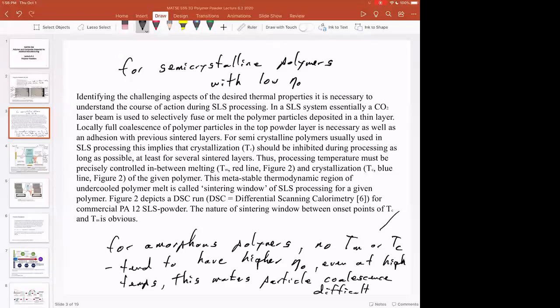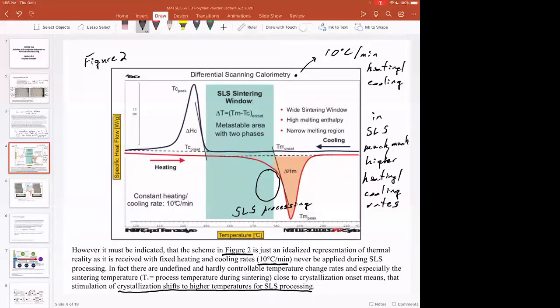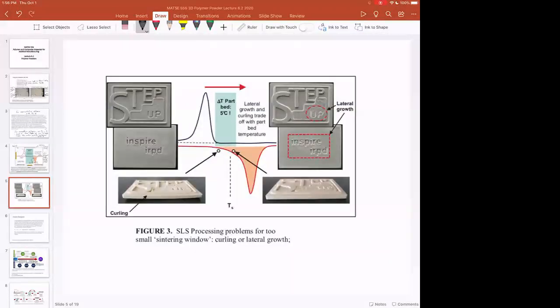And so that's one of the reasons why we don't have a lot of examples of amorphous polymers being used in SLS, because it's hard to get those particles to sinter compared to semicrystalline polymers that tend to have lower zero shear viscosities near their melting point. So that's sort of a compare and contrast about why this sintering diagram is important and what might happen at faster scan rates. One cool thing that they show in this paper is that if you're sintering,